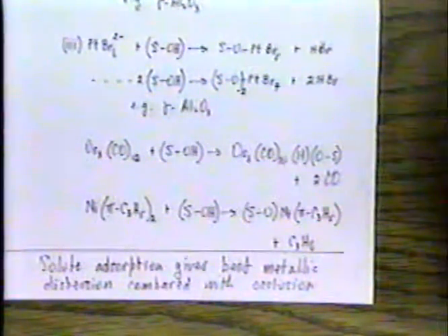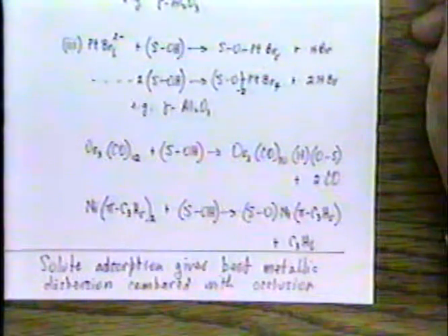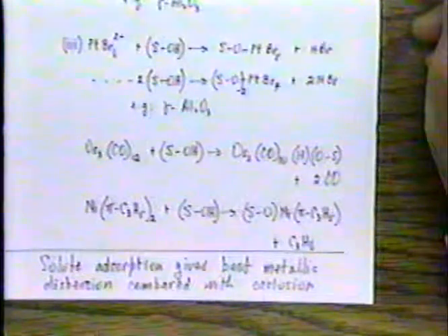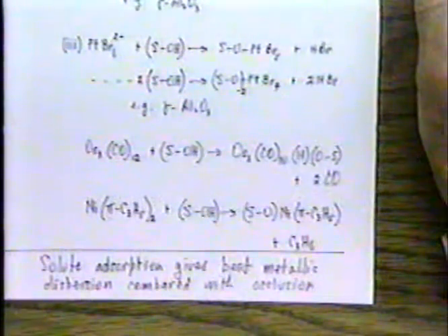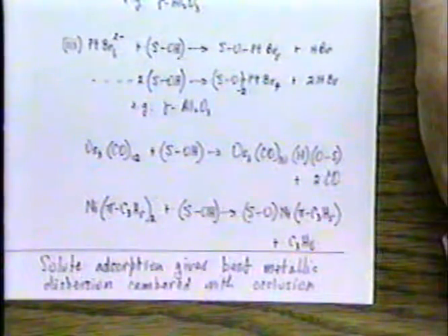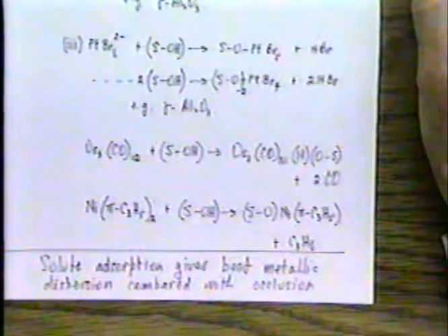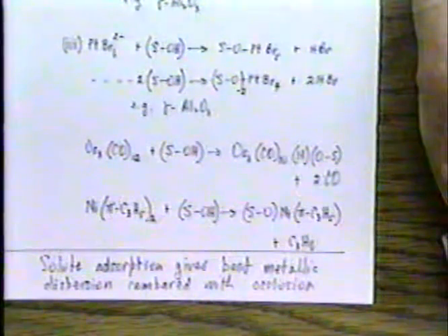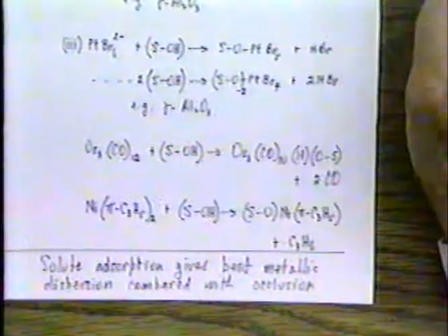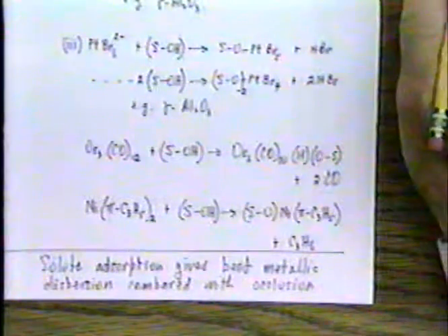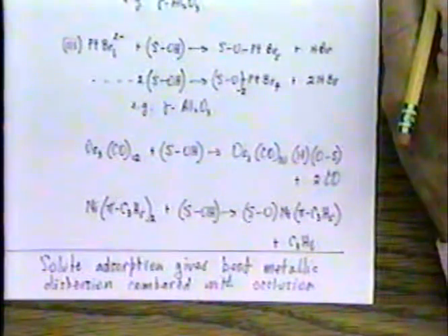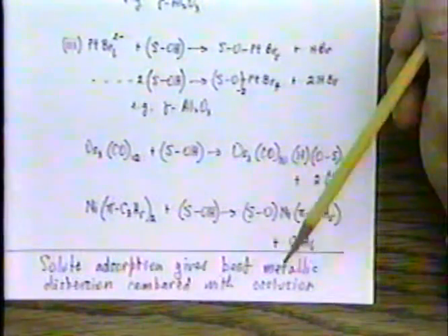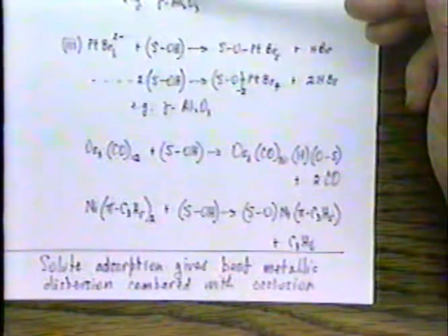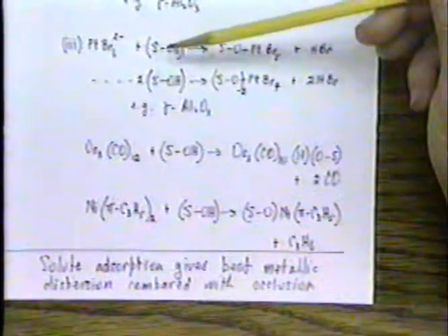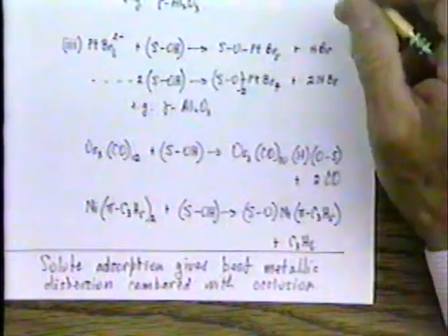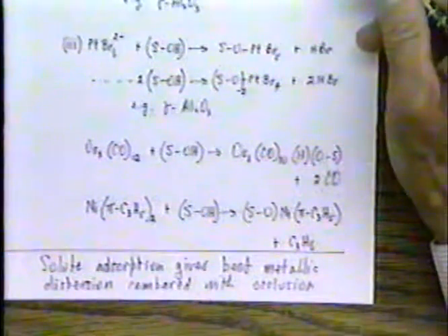The problem is, of course, with occlusion you have little control over the size of the metal particle because it depends very largely on the concentration of the solution being used for the impregnation process, and also upon the actual size of the volume of the liquid which is included in the pores of the support. And the result may well be, and very often is, that with occlusion you get largish metallic particles. If you want well-dispersed metal, you're better off, if you can, to work with solute adsorption or precursor adsorption techniques.